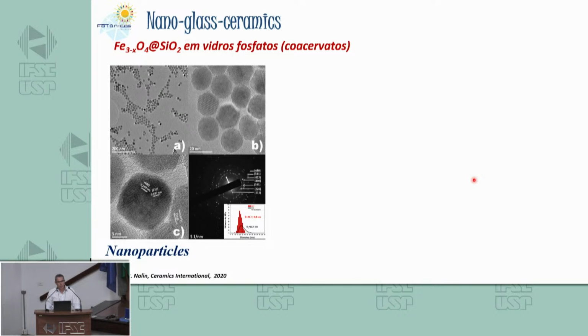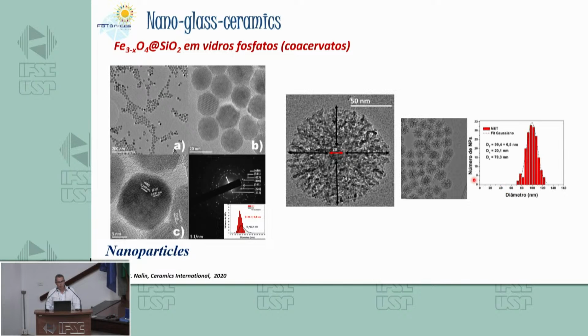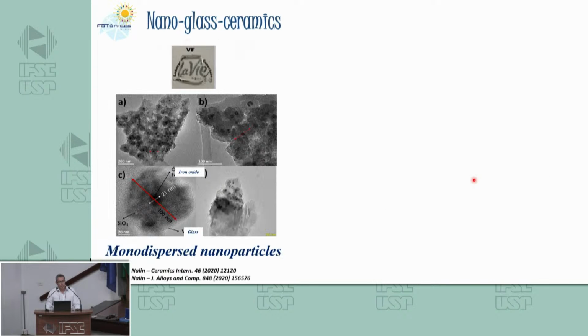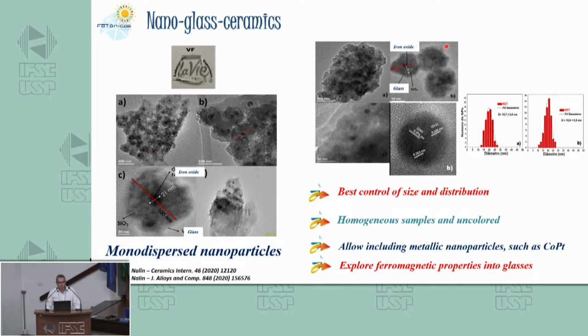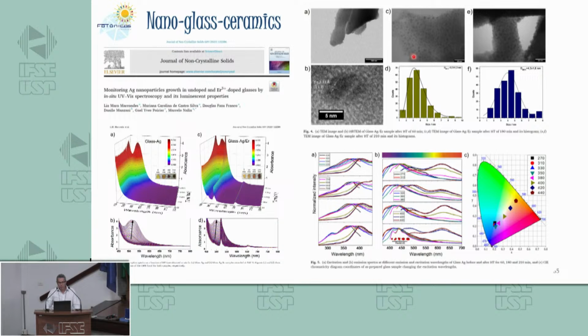We prepared the nanoparticles, then we covered them with the shell. This is a big nanoparticle. So the size of the nanoparticle with the shell is 100 nanometers, and then we put them into the glass. Here we can see the glass has no color. It was 8% in mass of silica and the magnetic nanoparticles inside the glass. Just jump a little bit here.